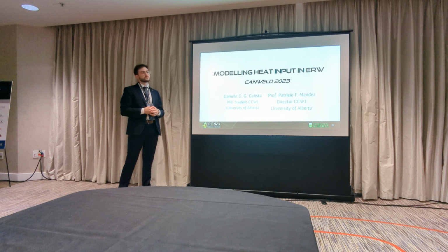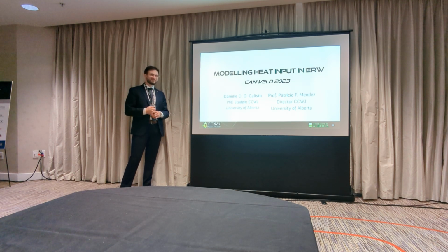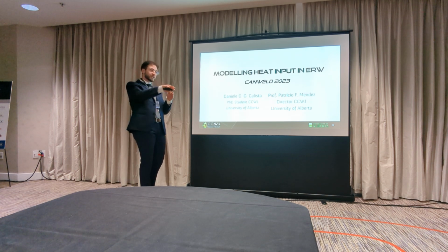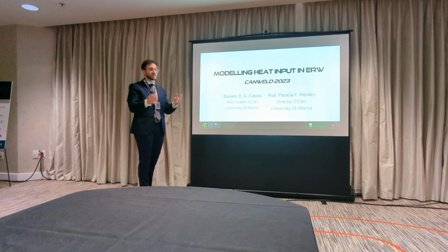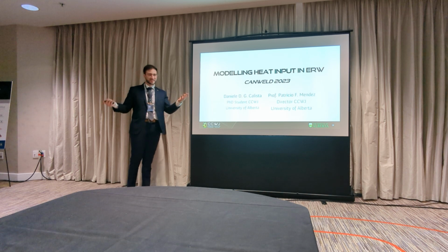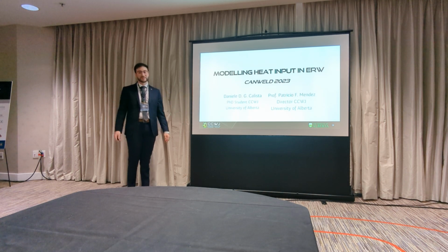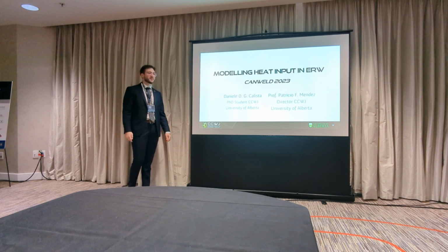Maybe a really dumb question because I don't know anything about this process, but have they ever considered shielding gases to help reduce the oxide? Even on the top, at least you get 50% of them. They have. Nippon has done plasma shielding, so they've actually shot a plasma jet into the V, removing the oxygen environment, and it successfully reduced penetrators significantly. Unfortunately, now you're running a constant gas stream, so the cost of your process became astronomical.